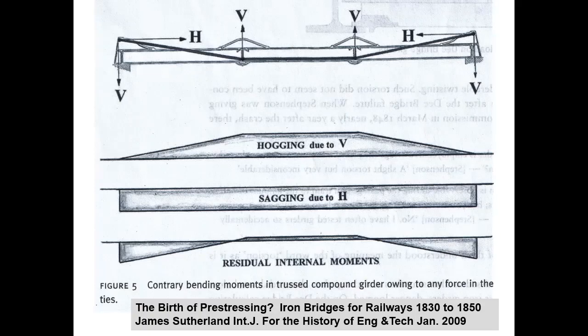James Sutherland in his paper showed this effect very well, illustrates it very simply here. If you try and relieve the girder of load using the chains with the forces upward V, all you do is induce horizontal loads at the anchorages H, which pull it down again. So you end up with no benefit, and the bottom diagram shows you the little bit in the middle of the span, the benefit you get out of it, which is absolutely negligible.